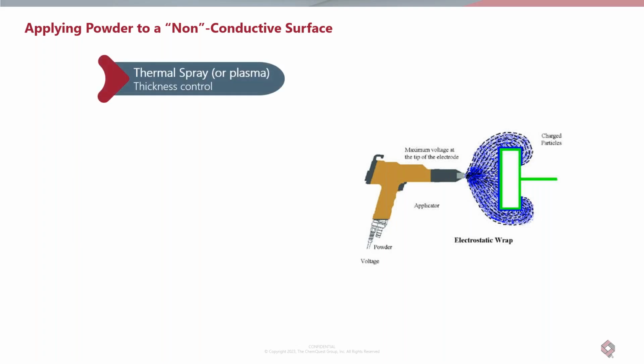I've done extensive work through the years. One of the concepts is having some heating process at the tip of a spray gun that's propelling powder into a space. People have worked with thermal spray, which basically puts some type of flame arrangement at the exit of a gun, causing the powder to become molten, and the molten powder is directed towards a surface. The problem with that is it's difficult to control thickness. You might be able to do this with a thick film where the thickness isn't very critical, but it's not the best option.